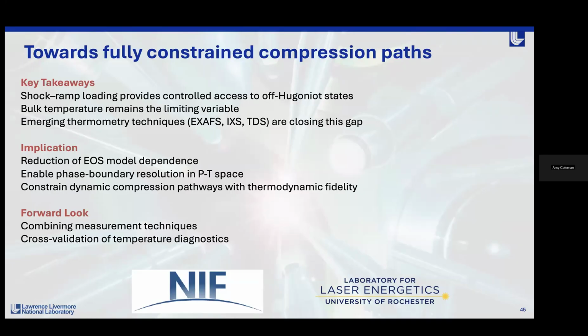So for me, the key takeaways are this: developments in laser pulse shaping have given us this tremendous gift. We're now able to field experiments that explore the space between a Hugoniot and an isentrope. But if we want to establish this technique as a robust way of mapping out phase boundaries and melt curves at extreme conditions, we need these reliable bulk temperature measurements.